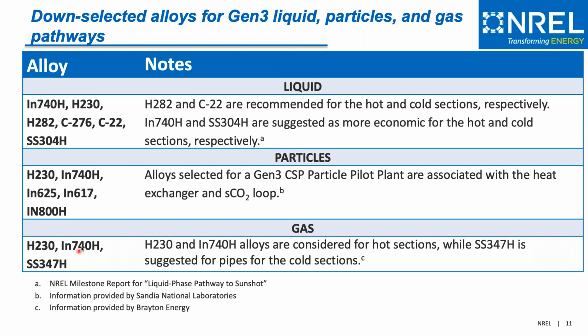But if you see, the common ones here are the Haynes 230 and the Inconel 740H in all the three. Why? Because they are giving you the creep and fatigue at the high temperature. But we know that Haynes 230 is difficult to print. We demonstrated that with two projects that we have, one with Elementum 3D and another one with UC Davis. The ones that are close and can print pretty well are the Haynes 282 and the Inconel 740H.